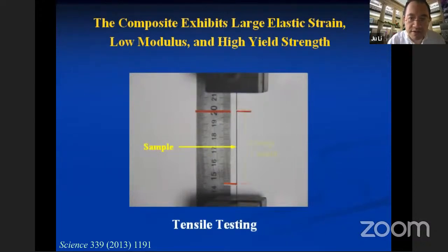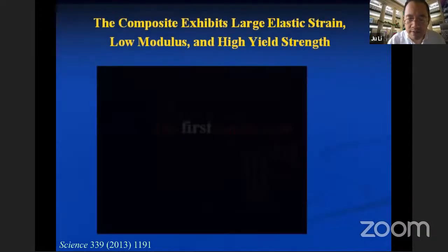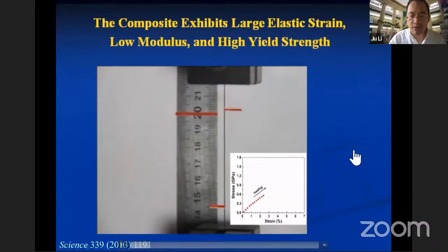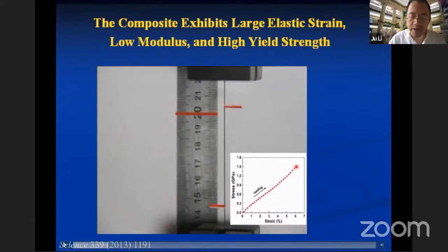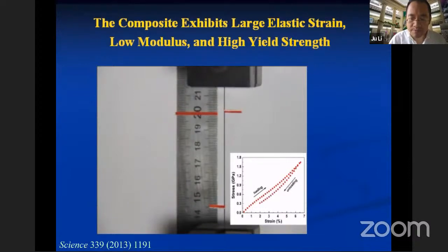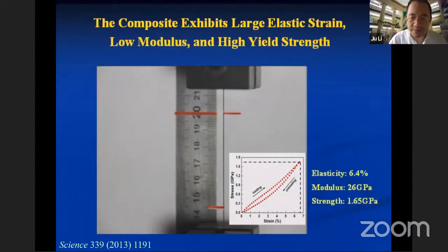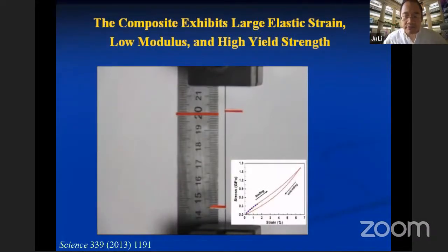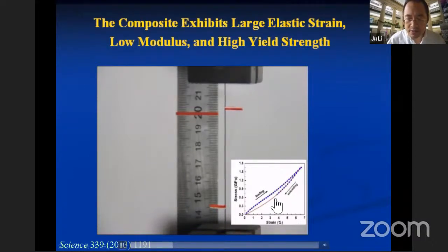So this was the first tensile strain. And for a metal wire, for a metal cable, this is not surprising, right? You can strain a metal by 6%. But if this were plastic deformation, as you unload, you would have 6% plastic strain. But in this material, when you unload, it goes completely back to 0. And so there is some hysteresis because of the phase transformation of the nitinol matrix. But overall, this stress is very high.